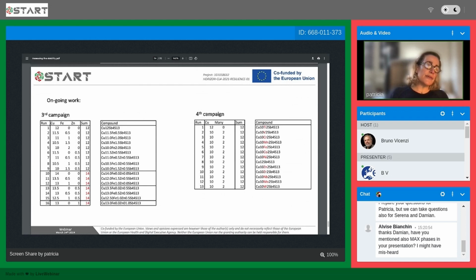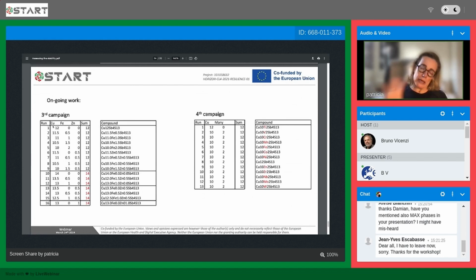So in this third campaign, what we're trying to do is for the composition in which the copper and the transition metals are 12. So we have 10 copper 1 plus, and 2 coppers 2 plus. Then in this third campaign, we are using iron and zinc to replace and then measure thermoelectric properties, in order to also calculate what we are expecting in terms of behavior with simulations. And this is in fact the composition which has been selected, around this, with iron and zinc, and around these proportions.